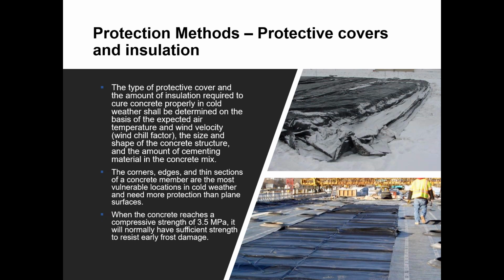When concrete reaches a compressive strength of 3.5 MPa, it will normally have sufficient strength to resist early frost damage. So we need to make sure that it reaches that minimum compressive strength. However, if you're going to be removing the protection and insulation of the concrete element, it needs to reach a minimum of 75% of the strength to make sure it withstands freezing and thawing cycles.